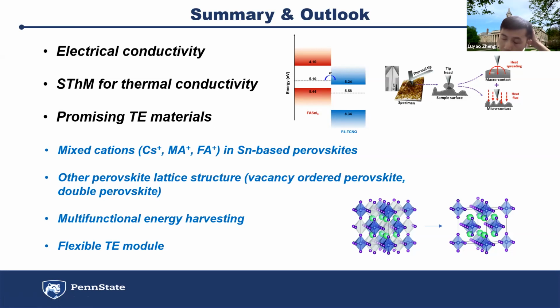And also we can probably try to use other structures of the perovskite, let's say the vacancy ordered perovskite. Basically, we remove the B-site metal from the typical 3D perovskite, so we generate more room and space for the cation to move and rotate. Probably we can get even lower thermal conductivity.